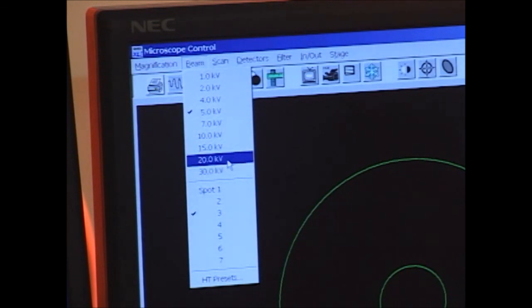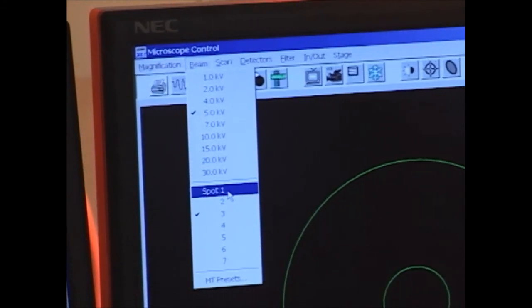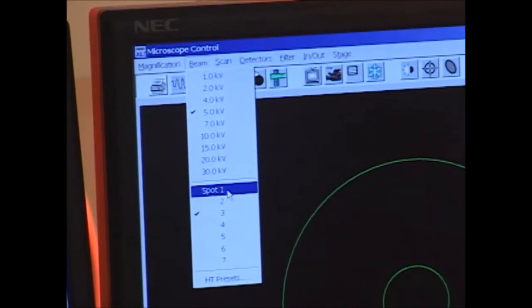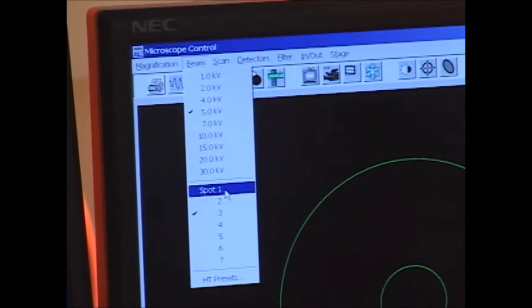Spot size then ranges from 1 to 7, 1 being the smallest diameter of electron beam and 7 being the largest. Spot size 1 also has the least current, and so it's again less damaging, and it's also the highest resolution. But because it has less current, it also has more noise, so it's a lower signal to noise ratio.